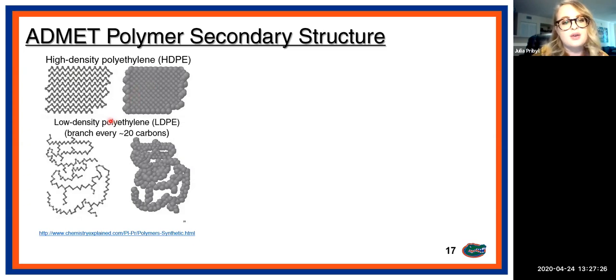Now, if you introduce a branch, a carbon branch, approximately every 20 carbons, but not in a precise manner, as in the case of low density polyethylene, what you end up with is a secondary structure that's much more disordered. And the reason for that is because the polymer can't really figure out a way to incorporate those branches into a nice regular crystal structure. So what you end up with is the sort of amorphous material.